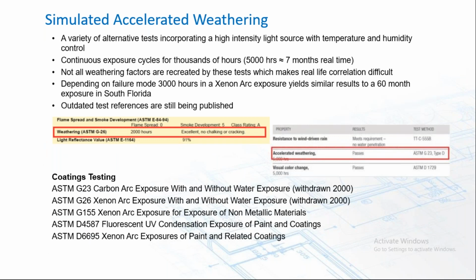Simulated accelerated weathering. Well, this is the automotive crash test of the coatings industry. We simulate accelerated weathering by applying our coatings to these test samples and exposing them to rigorous weathering cycles in laboratory conditions. They incorporate a high-intensity light source, temperature, humidity, and we expose these for continuous cycles of up to thousands of hours, 5,000 hours, and actually 7 months in real time. Depending on the failure mode, 3,000 hours in a xenon arc exposure chamber yields similar results to a 60-month exposure in South Florida. And that's a pretty extreme environment with UV, salt-laden air, winds, and rain.